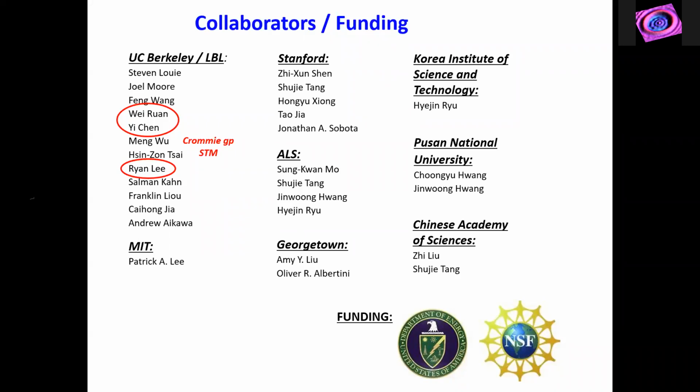And then the second question is the transfer. The data that I showed you, we did selenium capping. That's the answer. They grew the films up on the hill at LBNL and capped them with selenium, and we brought them down and blew off the selenium in the UHV, and it worked pretty well. The capping doesn't always work for every material, but for this material it worked pretty well. Lately we've been doing vacuum suitcase. I think we've done some measurements with vacuum suitcase, but the selenium capping works pretty well for this system. Okay, thank you.